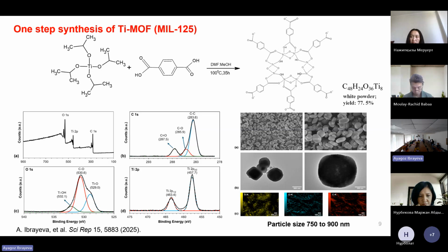Okay, understood. Another question. You told us that particle size is in a range, but did you calculate the average size of these MOF particles? By microscopy analysis, we looked at different sides of this powder, and decided it would be better to mention the range between 750 and 900. The bigger one was 900, the smaller one was 750.